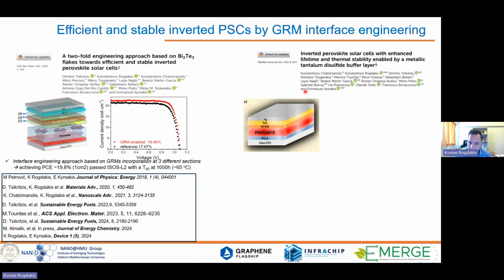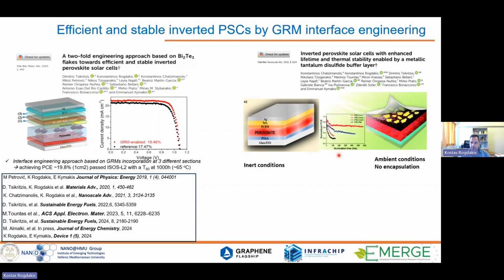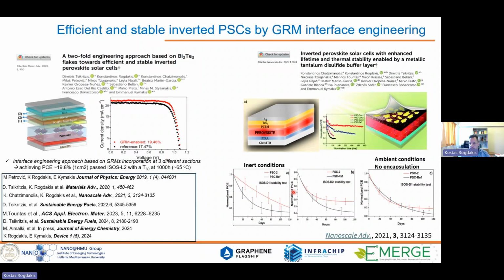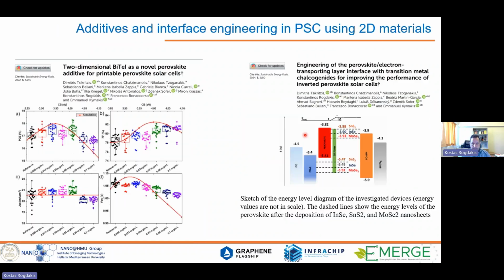Another approach was to use tantalum disulfide nanosheets, as shown here. Again, we developed a layer between the silver contact and the PCBM layer, and in this configuration, we demonstrated much better lifetime stability under various conditions using this interlayer formed by the 2D materials. Here, another approach was to use bismuth telluride iodide as a dopant inside the perovskite layer. We demonstrated that we can find the best concentration of these nanosheet-based inks in order to improve the power conversion efficiency.